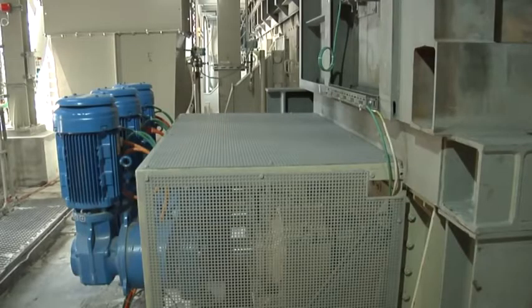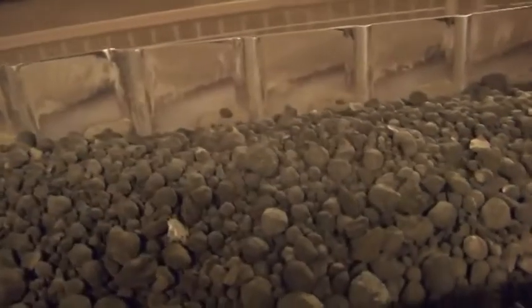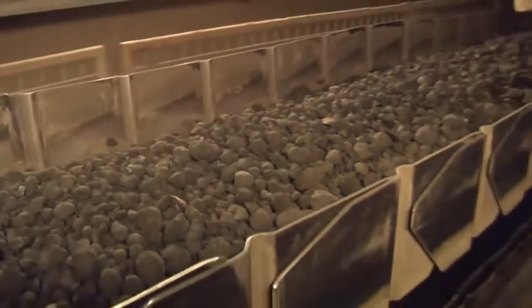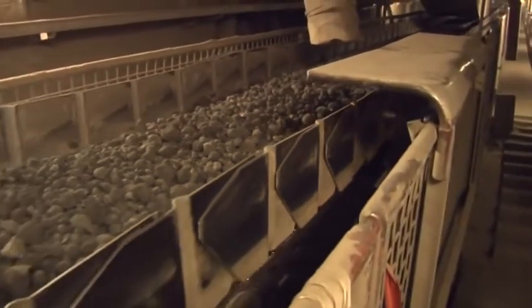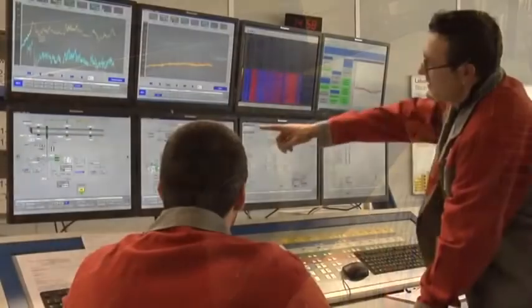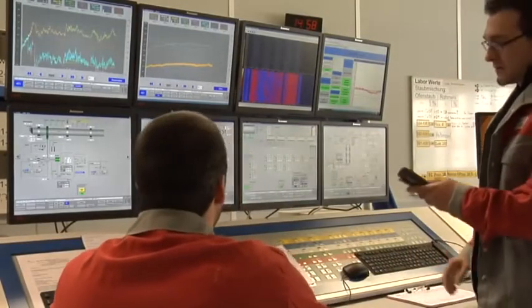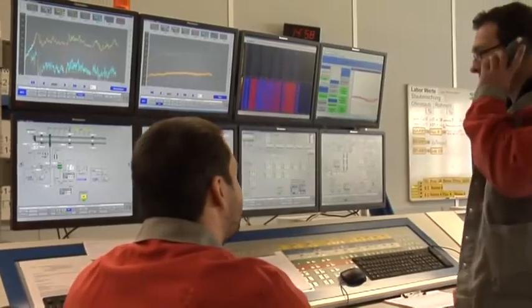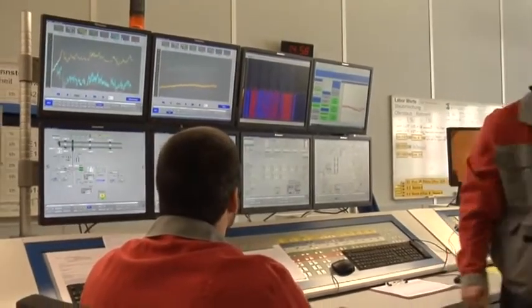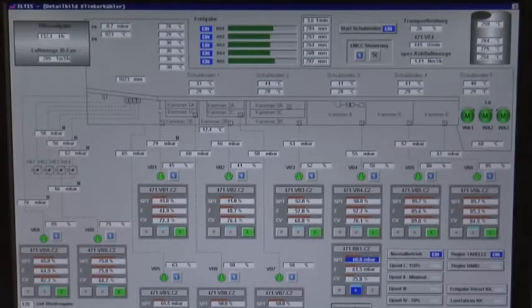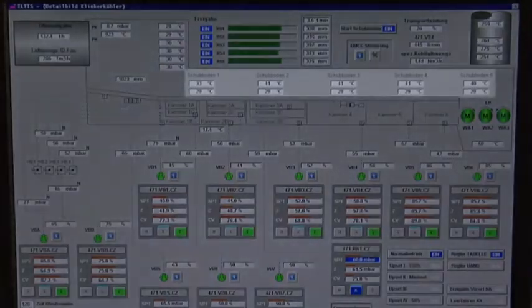Oversized lumps are crushed by the roller crusher. The cold clinker is transported to the clinker storage. Quickly, the optimum setup for the cooler is found by Holcim operators. The lanes are well protected by the gravel, therefore they only reach a temperature of about 40 degrees Celsius.